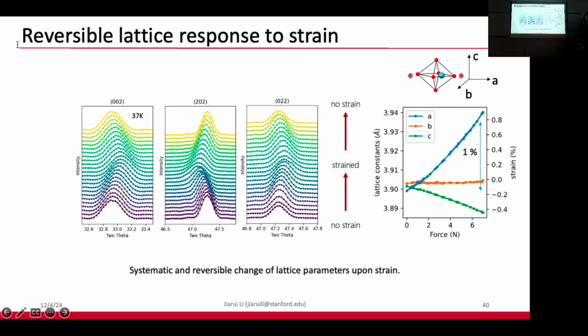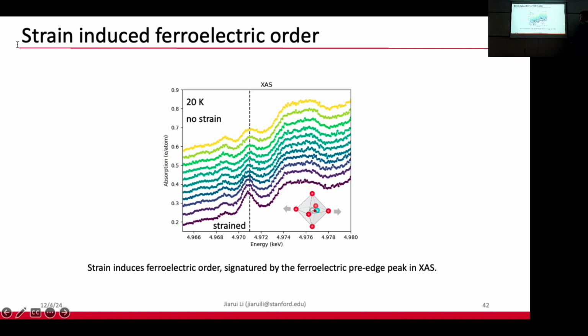Okay. So this is the basic characterization of the lattice and mechanical property of these nanomaterials. And in order to go into the physics, we measure the ferroelectric order by the titanium K edge absorption, where the photon energy is around 5 keV, 4.97-ish. And this is the photon energy, and this is the absorption of the X-ray by the titanium electrons. And we observe that when we increase the strain, there's a systematic change in this X-ray absorption spectra, that this peak is getting enhanced.